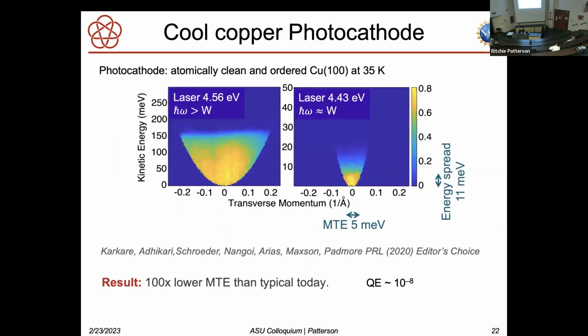The record for MTE was done with a cool copper photocathode by Sid Karkare and others, and their data is shown here. They took clean ordered copper 100, cooled it down to 35K, and there they were able to achieve MTE of 5 millielectron volts, and that holds the record. But as predicted, the quantum efficiency was very, very low. And that's a trade-off you're always going to have with a metal photocathode.